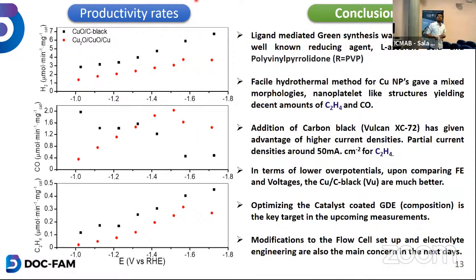And then when we look at the CO, the one with only copper is quite interesting, but it's getting less. But the good thing here is the one for ethylene, the one I prepared with the carbon black, was found to be quite interesting. Almost 0.5 micromoles per minute per 1 mg of the catalyst. So this is quite promising, we thought.